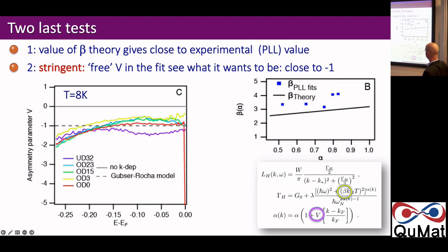Second one is a more stringent case. We then allowed the fit to work with this K dependence of the power law left free. It's a little bit scary because we have added 1 extra parameter to our fits, right? And we had to be careful how to do it, so that it didn't go uncontrolled. If it would be 0, you're back to your Lorentzian world. If Henk and Enea's model is strictly correct, it will be -1. And what you see is it's closer to -1 than to anything else. These are different temperature TC samples, all measured at low temperature here at 8 Kelvin. And you see as a function of frequency, they all share for the first 150 millivolts it's closer to -1 than anything else. So this is, I think, a very strong test of the theoretical picture.